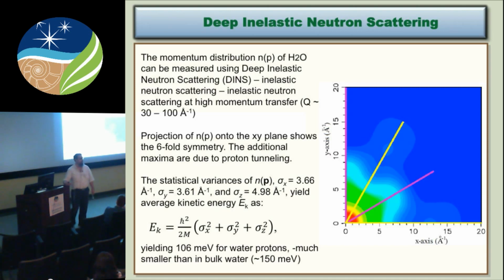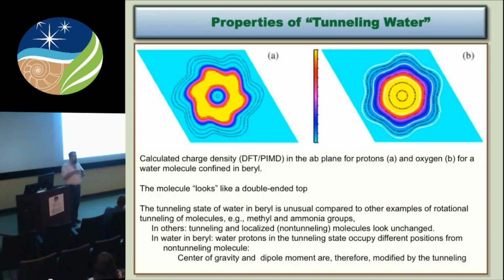It also showed, because you can get from the width of these peaks the average kinetic energy from those samples, that the kinetic energy for the water protons here, about 106 meV, is dramatically different from that you normally get for bulk water, about 150 meV, suggesting again that something is taking some of this kinetic energy, probably coming from the tunneling process.